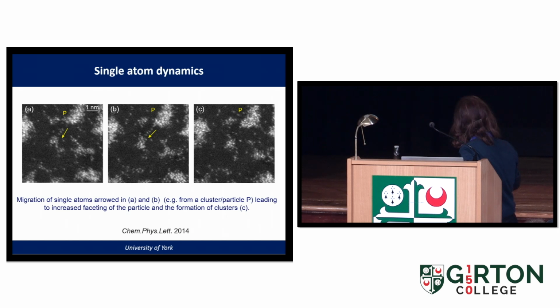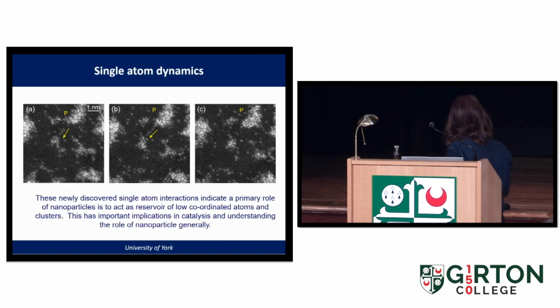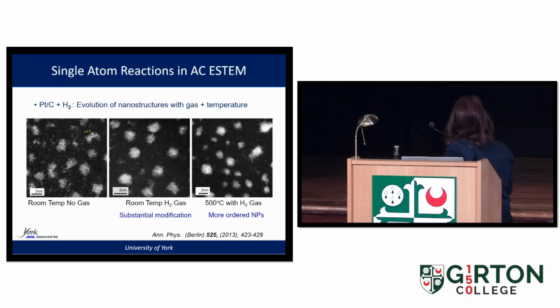But the bulk of the particle is actually not doing anything. So everything is happening on the surface. And again, they are disintegrating, forming a cluster. It's a completely dynamic process. So for the first time, we've been able to image these, and it's giving us insight into what's exactly happening. It's telling us that this bulk is not interacting very much. So basically, these particles are acting as a reservoir for these atoms and clusters on the surface. And when they give up these atoms, you can see the particle starts to become more and more faceted. So I'll come back to that in a minute. You can see that much more clearly here.